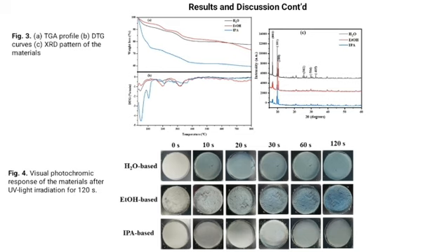For the XRD pattern of the heterostructured composites, it reveals diffraction peaks which are prominent at 2 theta equal to 6.9 degrees, 10.4 degrees, 10.6 degrees, 25.4 degrees, 29.4 degrees, and 32.5 degrees, which are in coincidence with the 001, 101, 200, 302, minus 502, and minus 405 HKL values revealed in the standard XRD database according to JCPDS file number 360101.